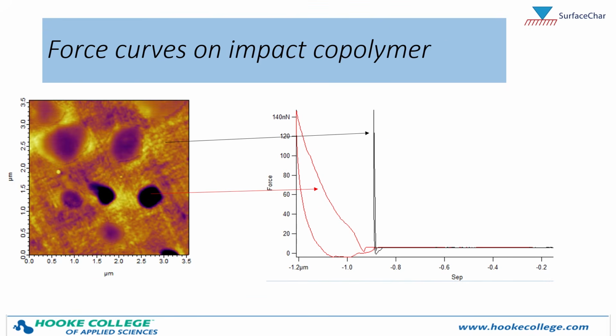Okay, so let's take a look at some real-life force curves from a sample material. What I have here on the left is a 3.5 micron by 3.5 micron image of an impact copolymer, or ICP. The matrix background here is a thermoplastic, and then these domains here are rubber domains. And so what I'm showing on the right are a force curve from the rubber domain in red, and a force curve from the thermoplastic matrix in black here.